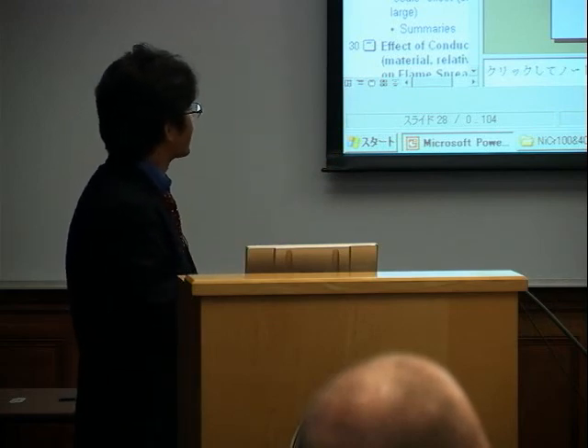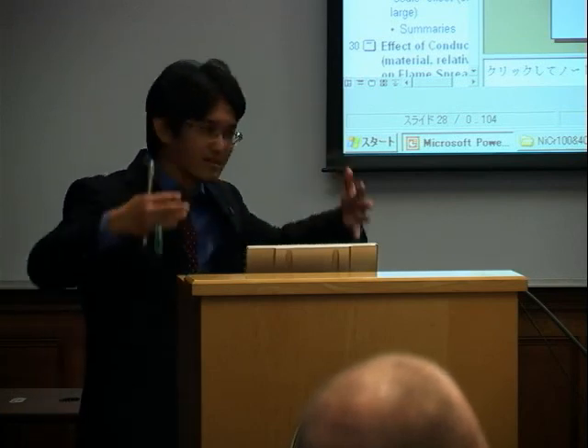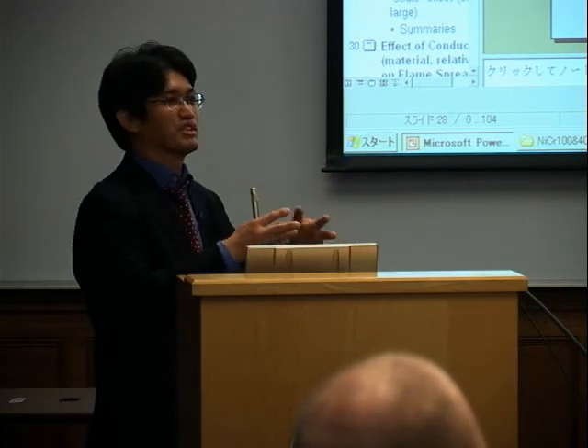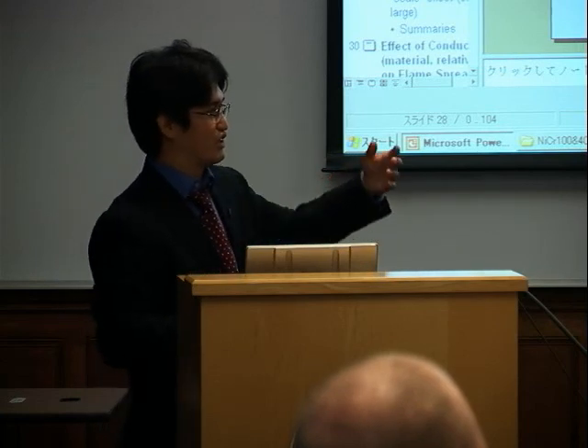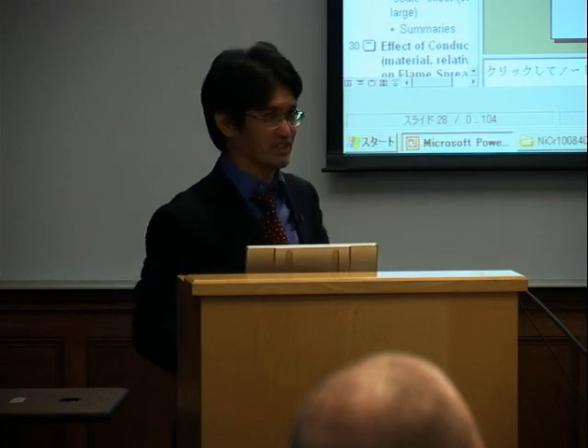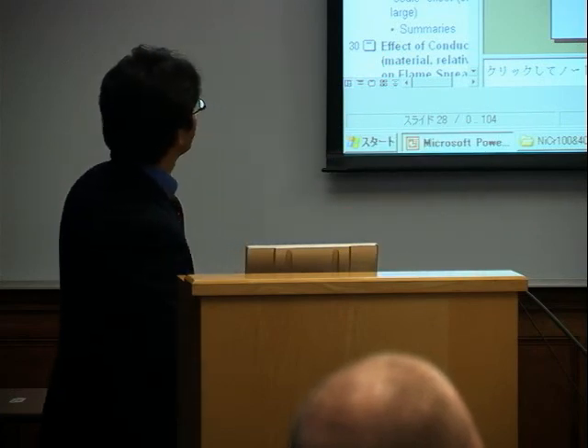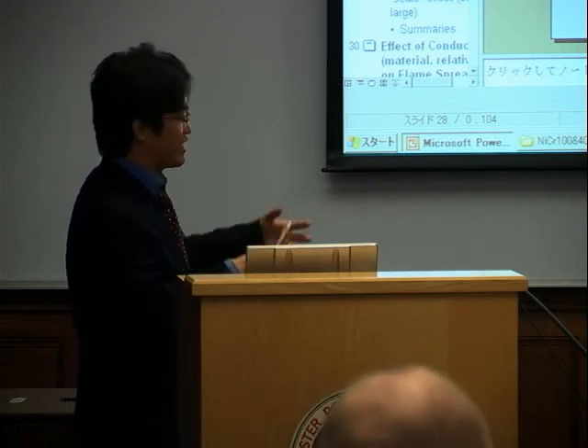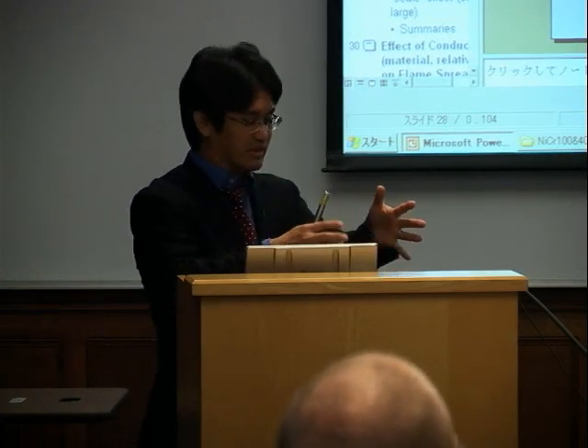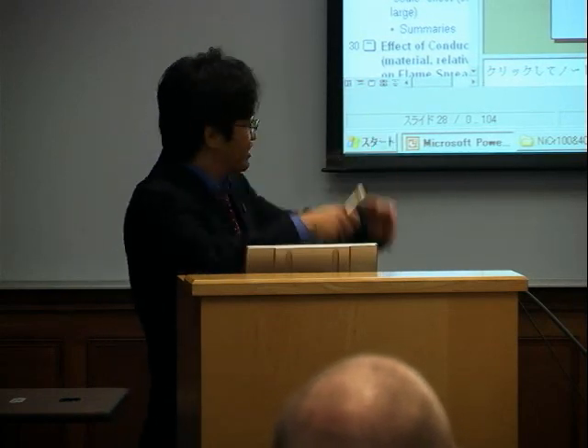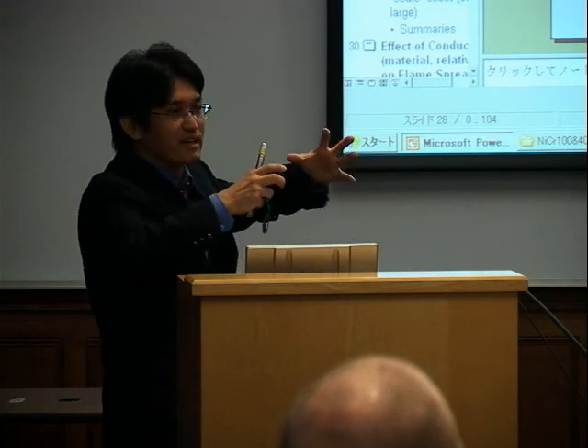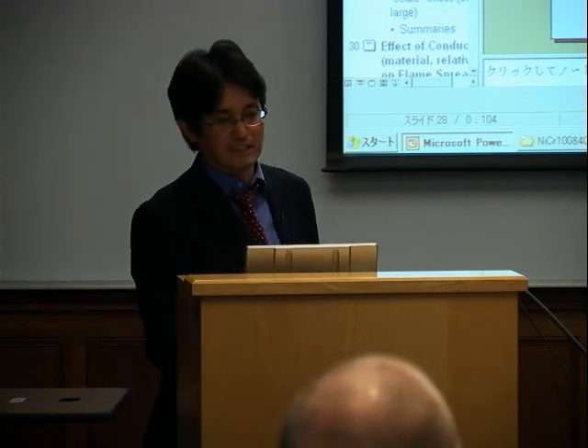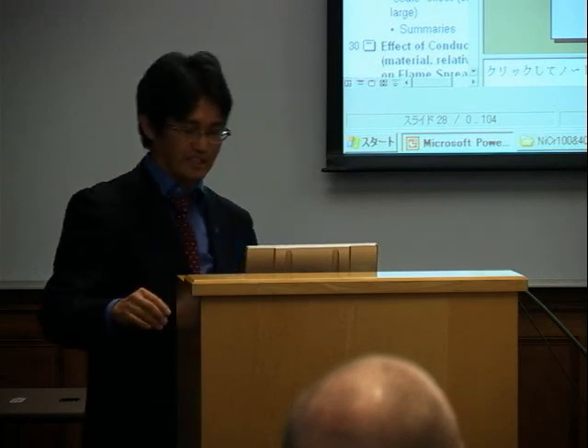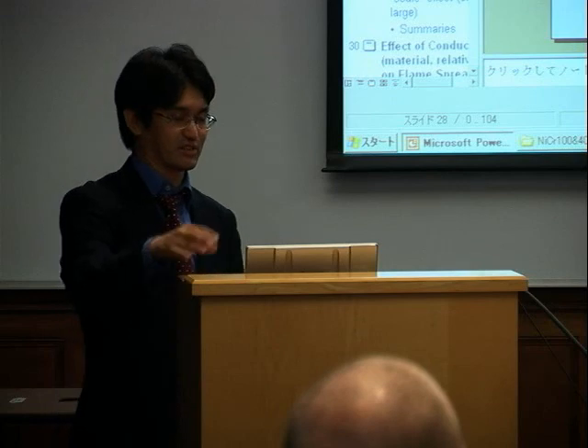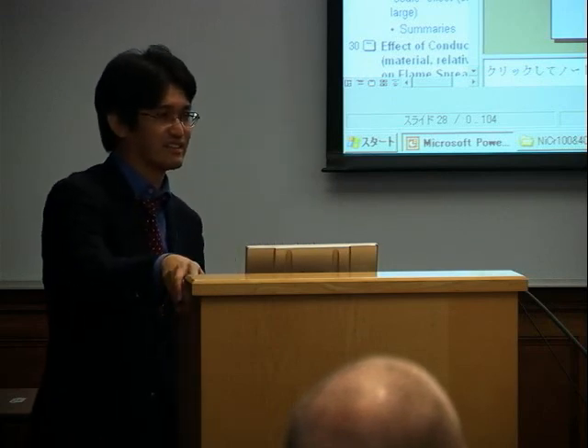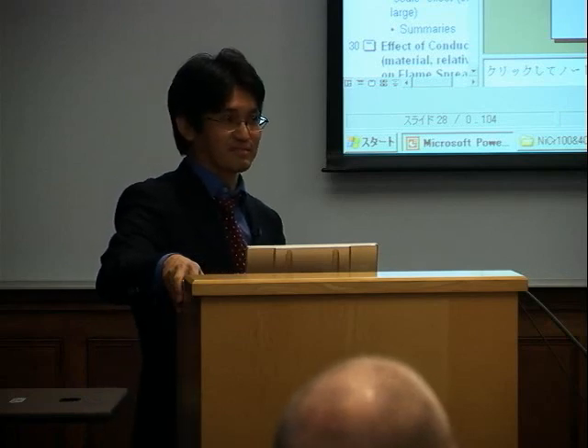If you go down to the low pressure case, you also have the same buoyancy flow. Your diffusion transport is more enhanced because there are fewer molecules there, so it's very easy for each molecule to diffuse. That's why around the flame, diffusion transport is much stronger than the buoyancy incoming flow. So you have expansion. So the flame shape is different, and I think this is very easy to understand how the flame spreading is getting higher. But I may be wrong.